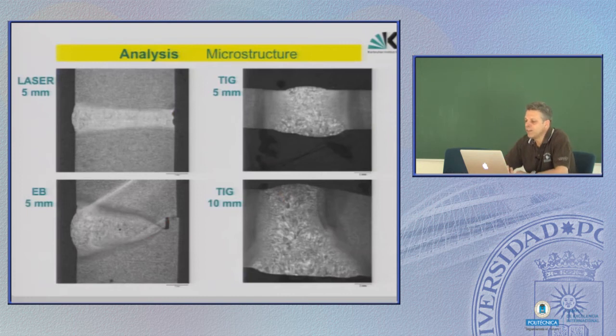Now let's have a look at the microstructure we have produced, as several parts. The laser weld has produced the narrowest weld line. It's only 1 or 2 mm thick. Then the electron beam weld, even though in that case it was not properly adjusted, produces a V-like shaped resulting weld, and depending on the thickness of the plates, this half V-shaped tungsten inert gas weld produces very big volumes looking like that.